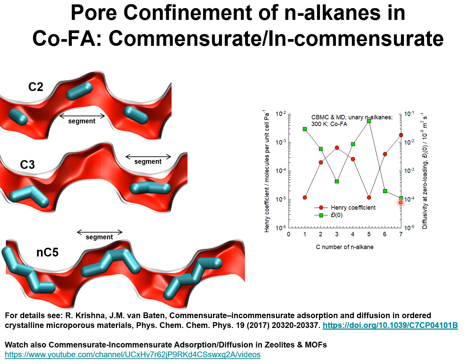Therefore, the non-monotonic behavior of the diffusivity with respect to chain length can be understood in terms of the snugness of fit within a channel segment, the commensurate or incommensurate nature between the length of the molecule and the length of a single segment or two segments. For further details, have a look at my publication of 2017 and also watch the video on commensurate, incommensurate adsorption and diffusion in zeolites and MOFs.